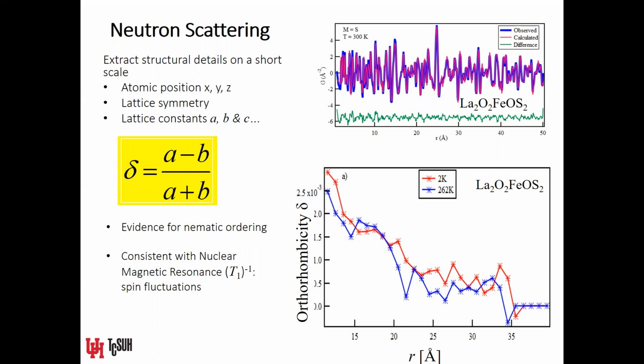What we did was we took the A and B lattice information and put that into an expression for the orthorhombicity, which tells you basically the deviation of A and B from each other. So in a tetragonal symmetry condition, A and B are the same. You expect to have no orthorhombicity. But as A and B begin to take on different values, then you should have a non-zero orthorhombicity. So we're calling that delta, and we're showing that.